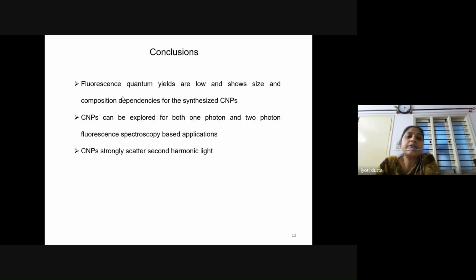Now, in conclusion, we would like to mention that these carbonaceous nanoparticles are not showing very high fluorescence quantum yields, and these quantum yields are having dependence on the size and composition of the synthesized carbonaceous nanoparticles. Further, we can see that these particles have a very broad multiphoton fluorescence background. So we can say that in addition to linear properties, they are also having nonlinear properties. So they can be explored for both one photon as well as two photon fluorescence spectroscopy based applications. Further, they are strongly scattering the second harmonic light. So they must be explored for the beta measurements and further details.